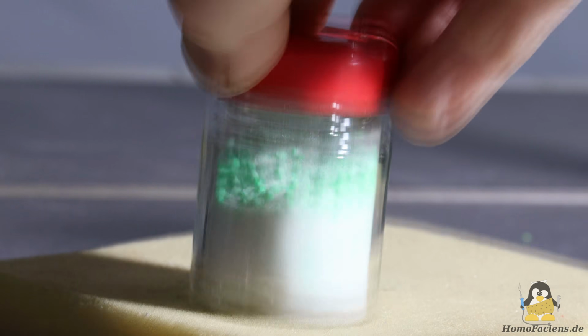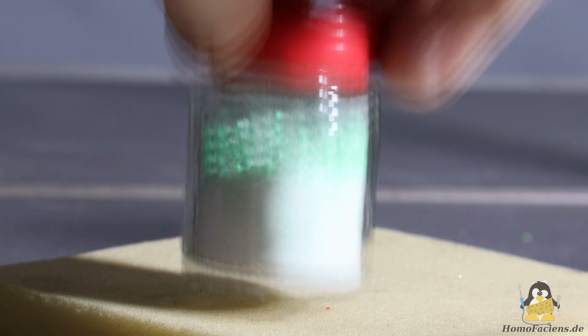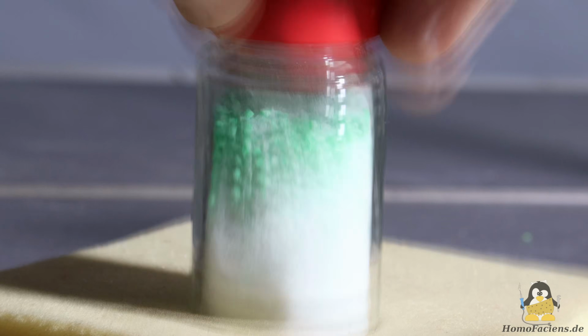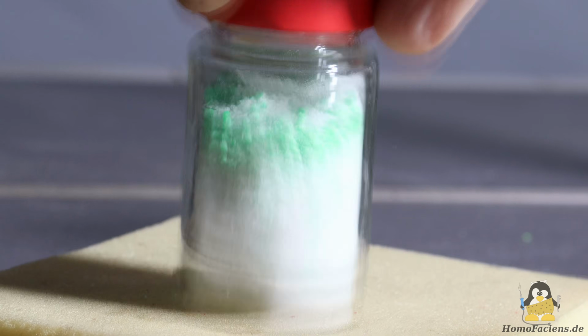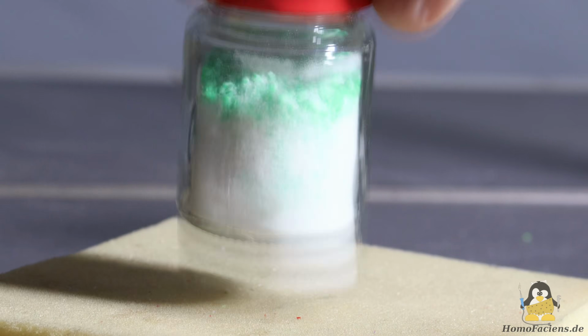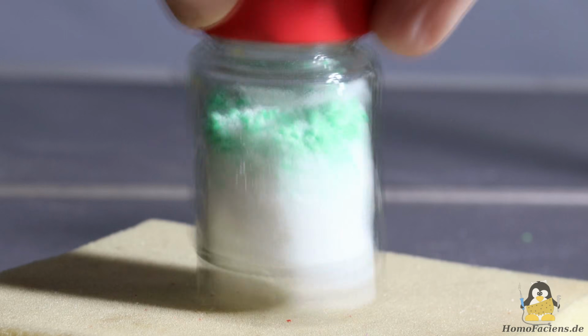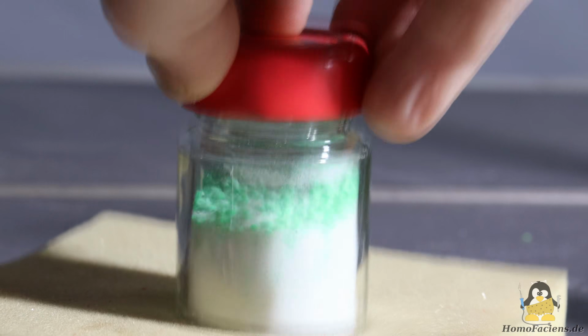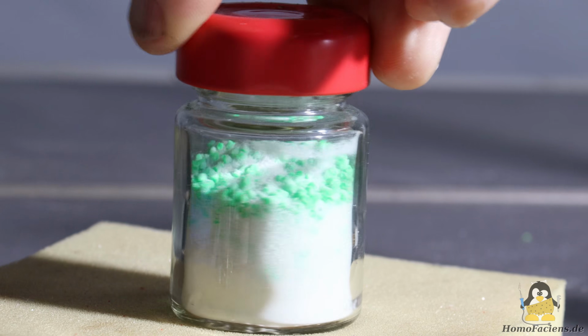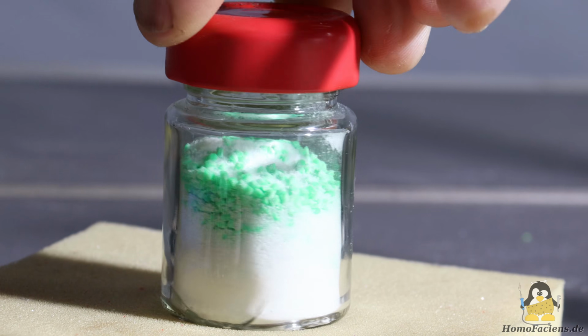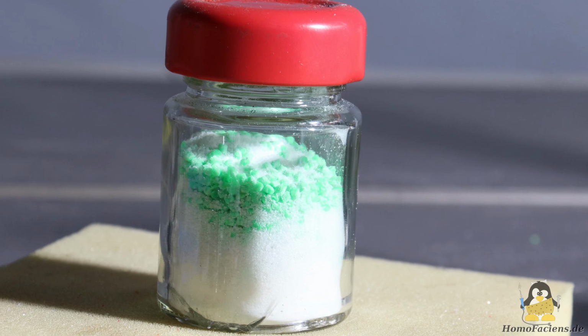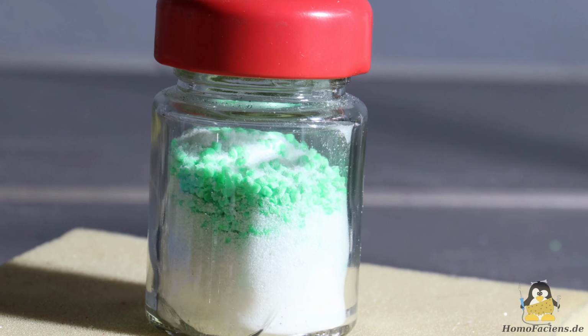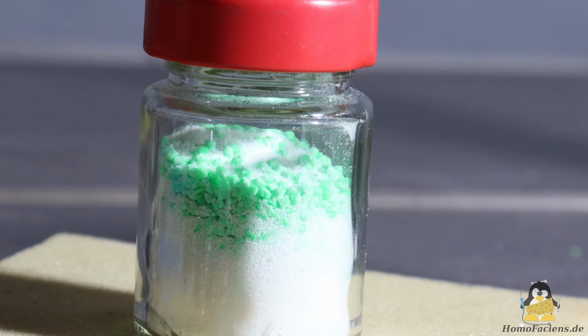Here I have filled a glass with a mixture of the industrial powder and the green pellets. Now the glass is shaken for a few seconds, simulating the movement of the printhead and its hopper. You can see the large green pellets moving to the top, while the powder migrates to the bottom of the glass. The fill level is no longer uniform, and since the material intake into the extruder depends on it, this separation of the raw material must be prevented.